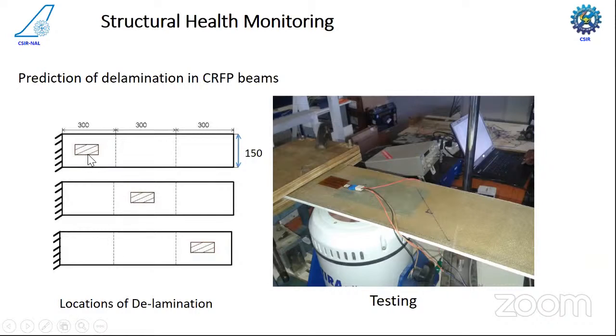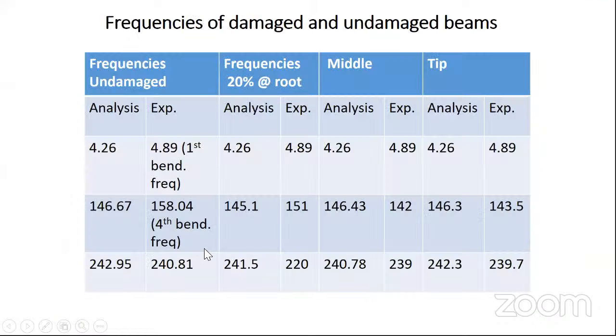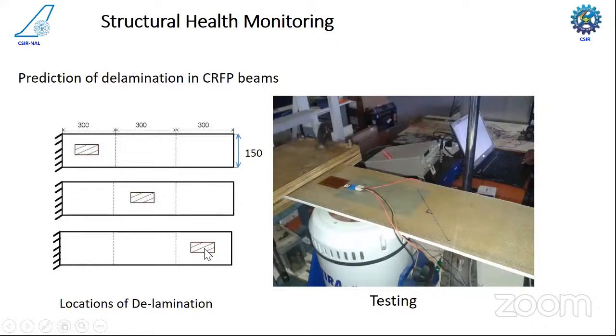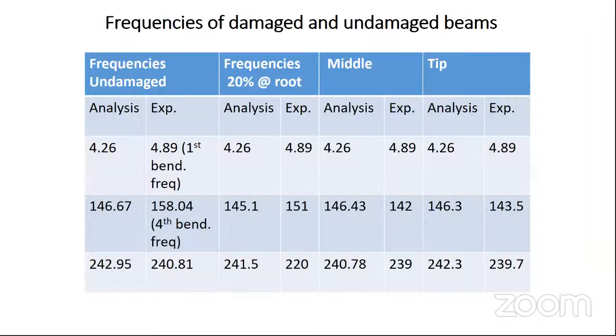at 3 different locations we considered the delamination. Basically, it is a study of the size of the delamination that we are able to find. So 3 levels, in the sense the root region, middle region, and the tip region. We have also carried out the analysis in Abaqus, and you can see both sets of data here in this table.